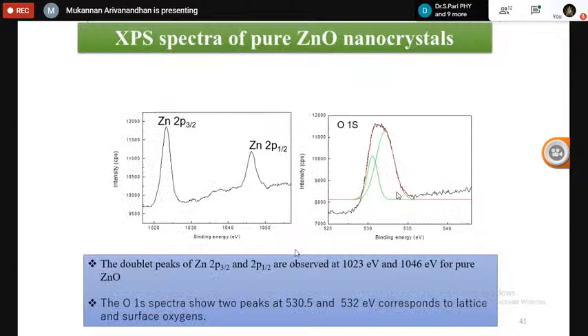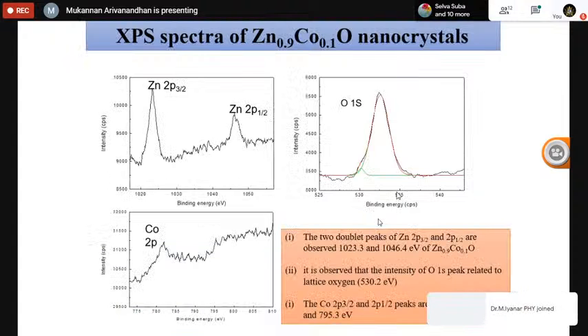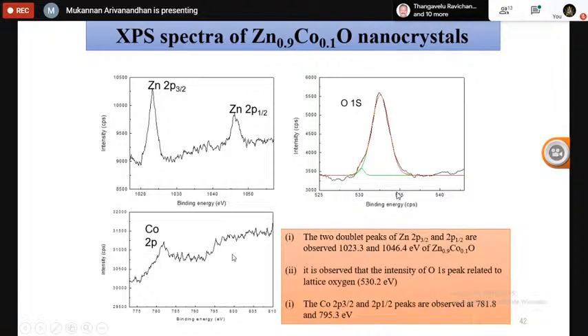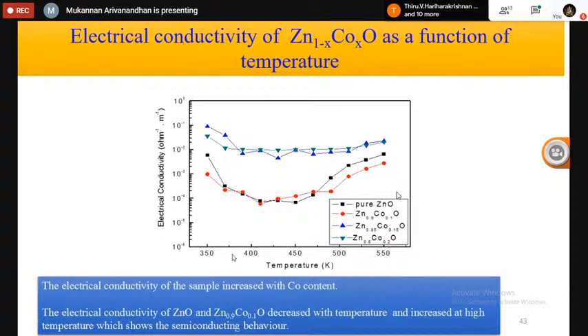Okay, and then once again, the presence of cobalt in the zinc oxide has been confirmed by the XPS. And look at the pattern, the XPS spectrum. It shows the Zn 2p and oxygen 1s spectra, and this is for the cobalt substituted system. So in addition to the zinc and oxygen, the cobalt peak has been obtained, which further confirms the presence of cobalt. And then the sample has been subjected to electrical and Seebeck coefficient measurement.